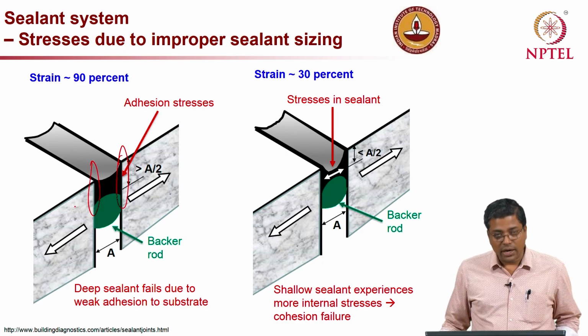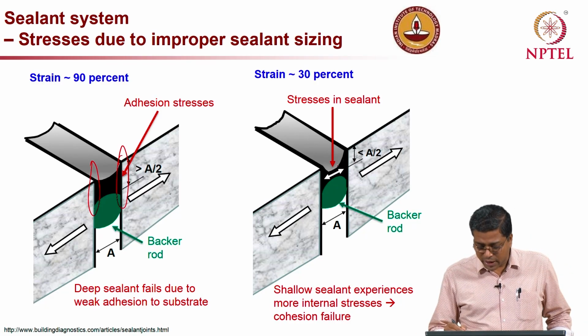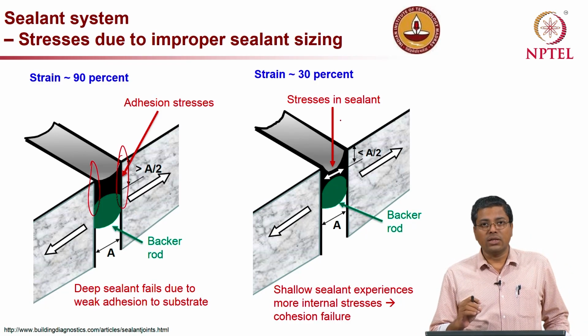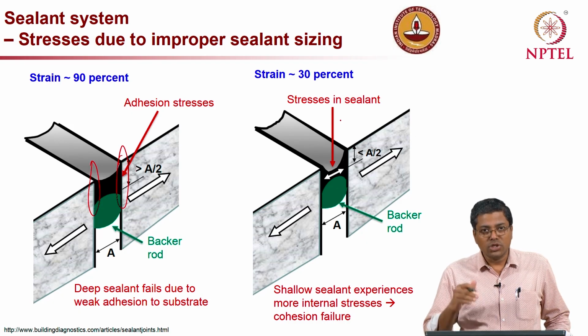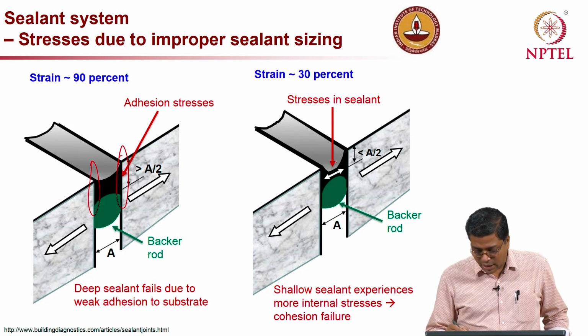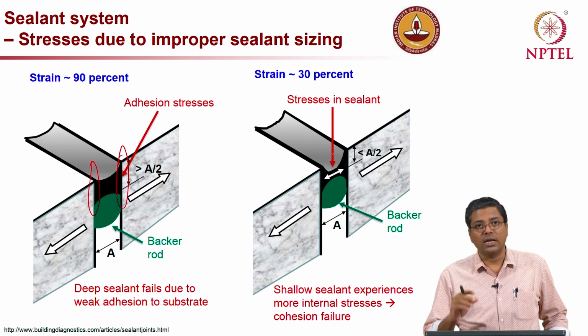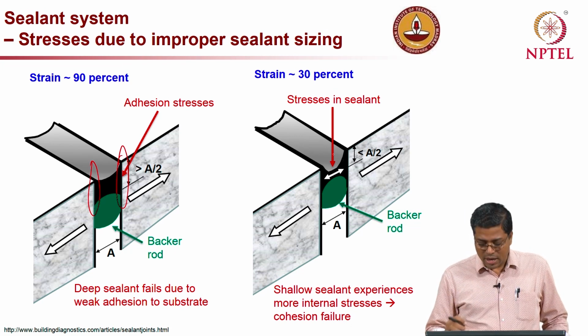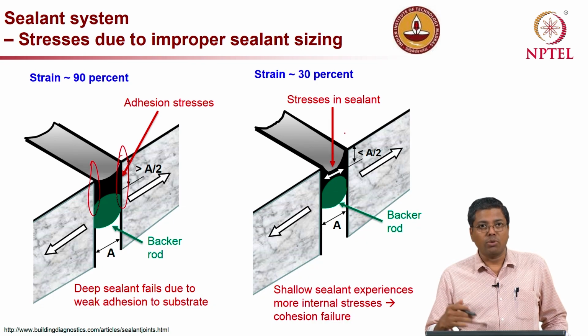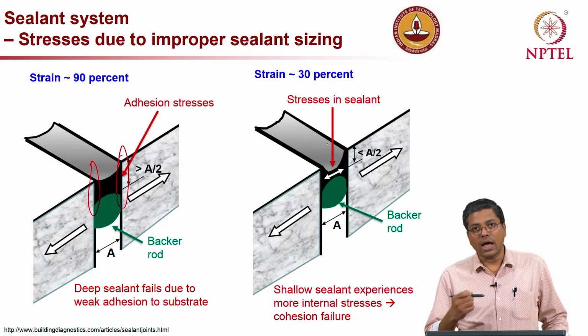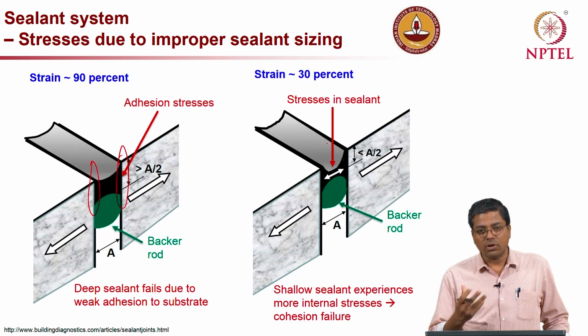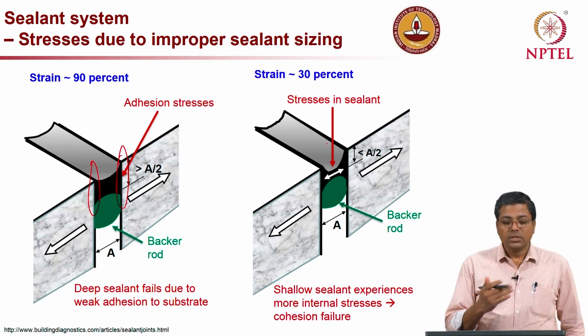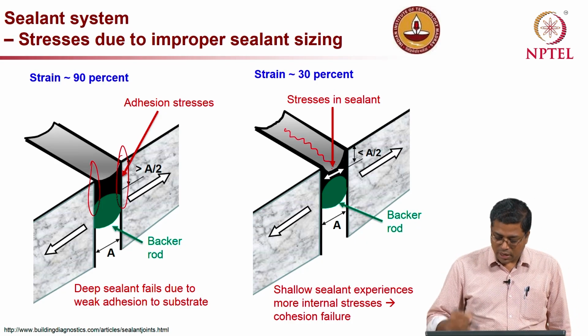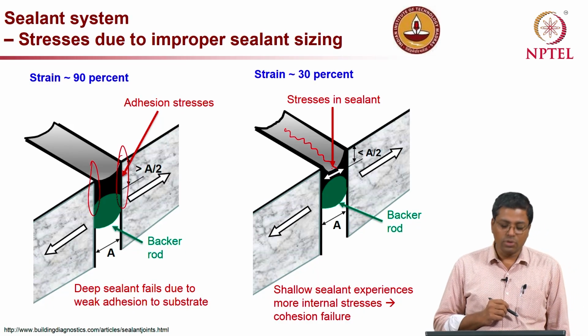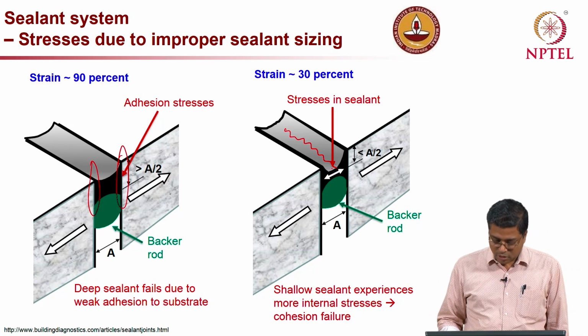The one on the right side is mainly looking at when the thickness is less, or in other words the backer rod is not deep enough. In such a case, the thickness of the sealant will be relatively much smaller, which will end up creating more and more stress at the center portion of the sealant, and then you will have a cohesive failure. In other words, the sealant will crack, something like this. That is how that system is going to fail in the second case: cohesion failure.